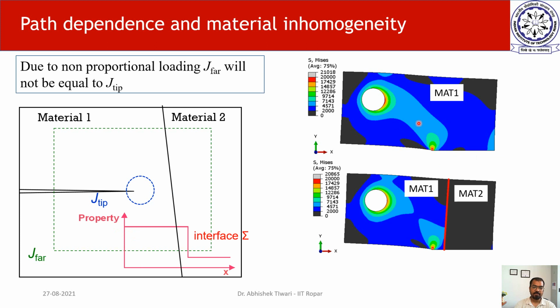Now imagine that I have a sharp transition of material, so it can represent a dissimilar metal weld along an interface, and here I have a transition from material 1 to material 2, and material 1 is having higher values of mechanical properties. So Young's modulus or yield strength is higher in comparison to material 2. It means that the crack tip, if it grows and crosses the interface, it will be a stiffer to compliant transition of the crack tip. In a very rough way, I can call it hard to soft transition.